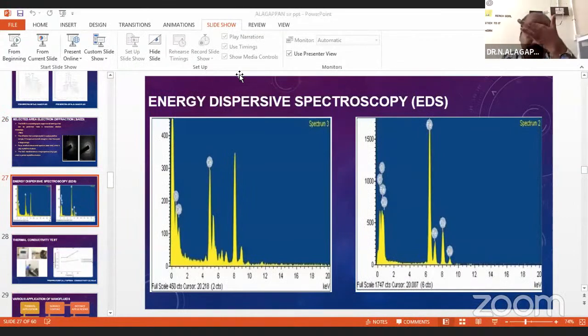And similar to Fourier transform, another method, energy dispersive spectroscopy. This is also to identify the composition of your nanoparticles, which means how much amount of Ce is present in the nanoparticles and how much amount of O is present in the nanoparticles. Similarly for Fe3O4, Fe and also oxygen, copper, carbon, everything will be shown in the energy dispersive method.